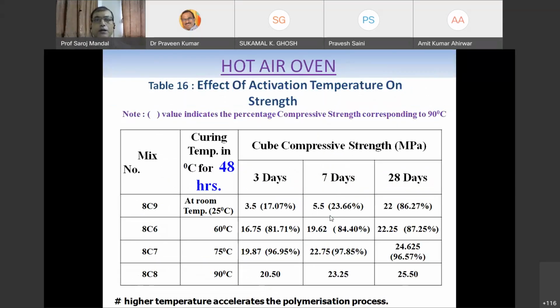Now come to the durations and temperature in the case of the hot air oven. This is the mix. You see, all mixes have 48 hours duration of curing or activation. This is room temperature, 60 degrees C hot curing, 75 degrees C and 90 degrees C. If you increase the temperature of curing, keeping the duration at 48 hours, strength increases from 3.5, 16.75, 19.87, 20.5. What you get is 3 days, 7 days and 28 days. For 28 days, it increases from 22 to 25.5.